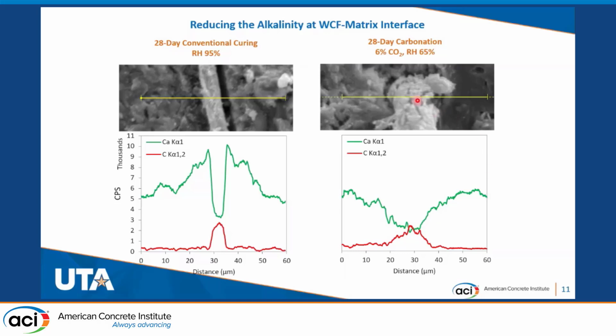The SEM-EDS analysis for the specimens after 28-day carbonation shows a significantly reduced calcium concentration at the fiber matrix interface here. And the presence of carbonates is confirmed by the diffused area here shown in the red curve between 20 and 37 microns.